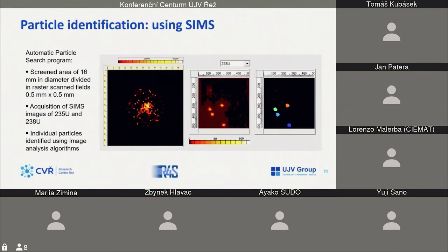In case of SIMS, we use imaging capabilities of that instrument, and we use an automatic particle search program, which divides the surface of the substrate into 500 micron by 500 micron fields, which is the maximum size for rastering of the primary ion beam. And we obtain ion images of uranium-235 and uranium-238. So we obtained two sets of images for every field on the sample. There could be hundreds of fields, or even more than 1,000, depending on the size of the field and on the size of the sample which we analyzed.